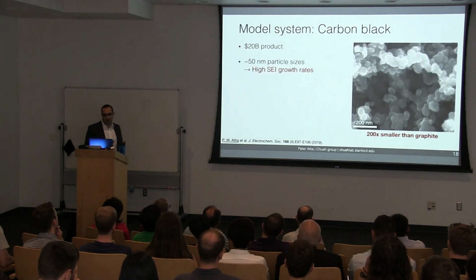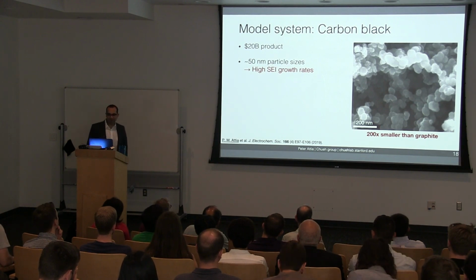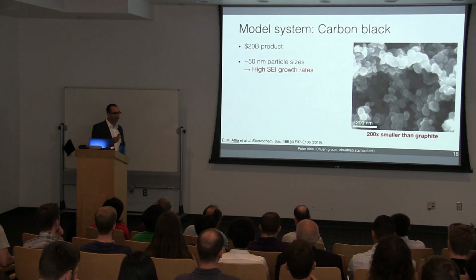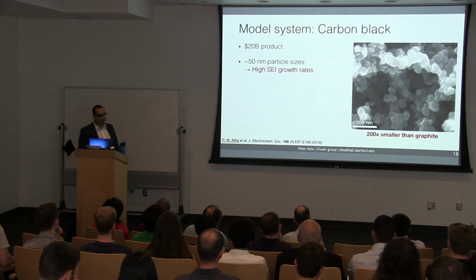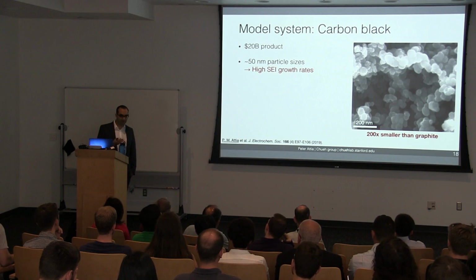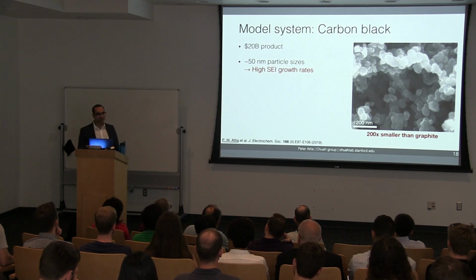Carbon black is also really small. The average particle size of the carbon black that we use is around 50 nanometers, which is 200 times smaller than graphite. The advantage of small particle sizes is that they have really high SEI growth rates. This means that carbon black is a bad material to make a battery with because we degrade it really quickly, but it's great for us because we want to study SEI growth.